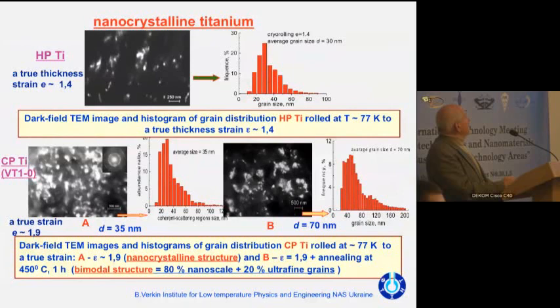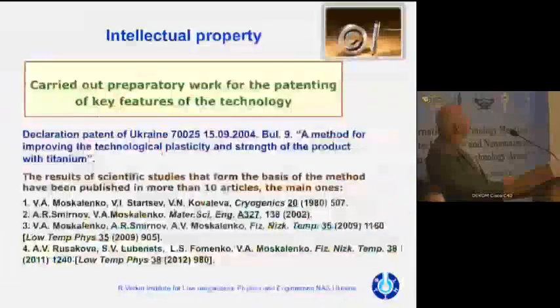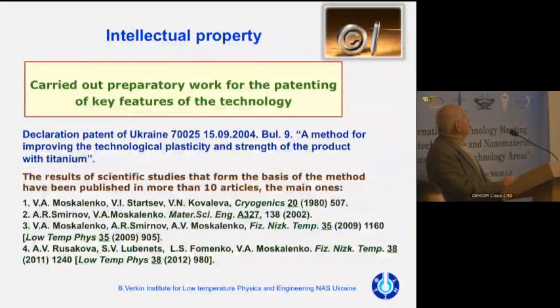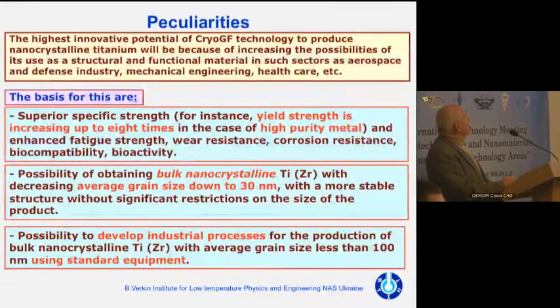But in order to break the threshold of plasticity while at the same time increasing the hardness, we suggest a bimodal structure, in which the nanocrystalline matrix will include a share of submicron size grains. We don't have patents, there's only a declaration of patent. And these are the results and the participants in these studies.